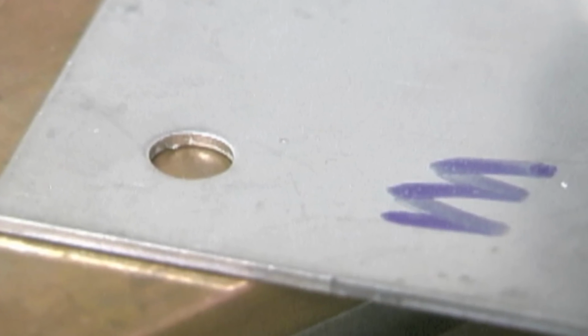It was no surprise. I'm going to weld some .050 stainless here, hole fill. Just filling. The common thing is to fill a misdrilled hole in some sheet metal. I am backing this up with a big chunk of solid copper. There's a good tip for you. Just hang on to all the copper you can get, because it comes in really handy for backing up stainless steel when you either don't want to take the time to use argon, or it's just not feasible or not economical. Sometimes just copper backing dead against the back of a hole like this is just as good, or, as for the purpose, it's good enough.